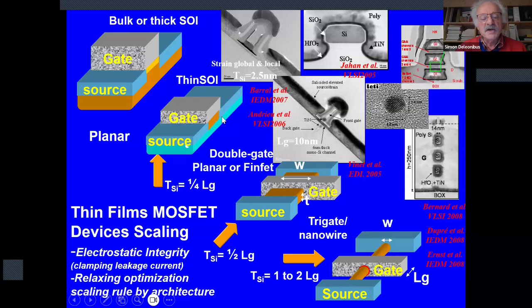So one of the ideas that was brought up was to use thin SOI in order to confine the charge in a thin film and avoid any bulk leakage that has been identified as a limitation to scaling. Furthermore, if we want to achieve ultimate scaling, we need to reduce this channel thickness, and to do that there has to be some rule that you can see here.